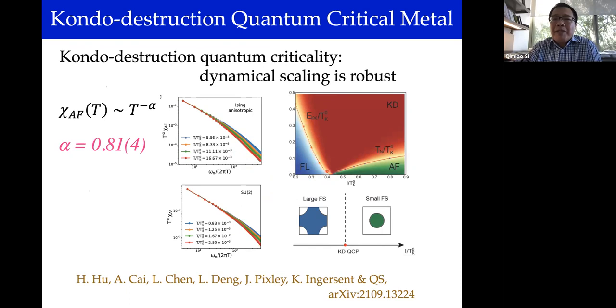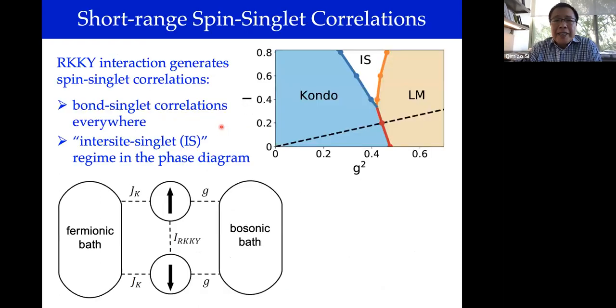So the same type of quantum criticality is being captured with a large to small Fermi surface sudden reconstruction at the quantum critical point. But also in the dynamics, the omega over T scaling, here it's the Monte Carlo calculation, so it's the imaginary Matsubara frequency, but the spin response at the anti-ferromagnetic wave vector is singular and with exponent, which is approximately the same as in the previous calculation, and has the omega over T scaling. So that sets the basis for analyzing the superconductivity.